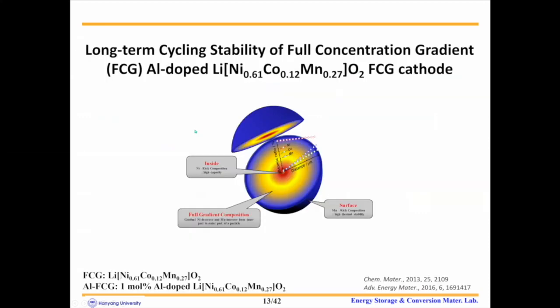This is one example of the concentration gradient. We synthesized two cathodes. One is FCG, full concentration gradient, with a nickel content over 61. The other one is a 1 mole percent aluminum doped FCG material called ALFCG. And then we compared long-term cycling performance of the two cathodes.